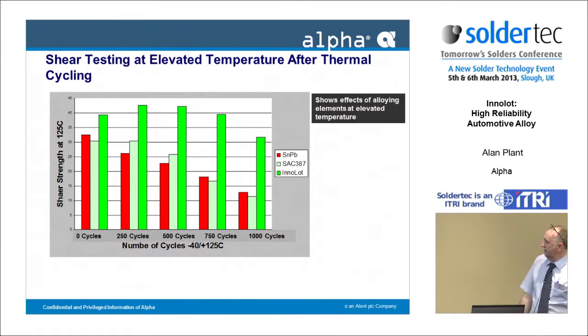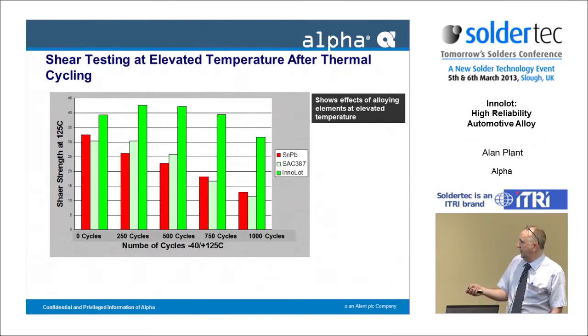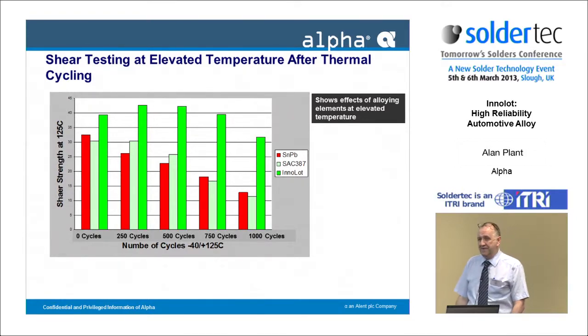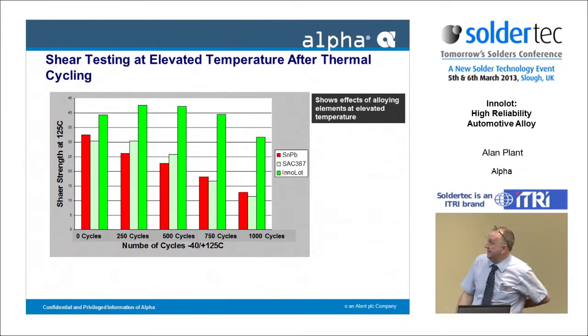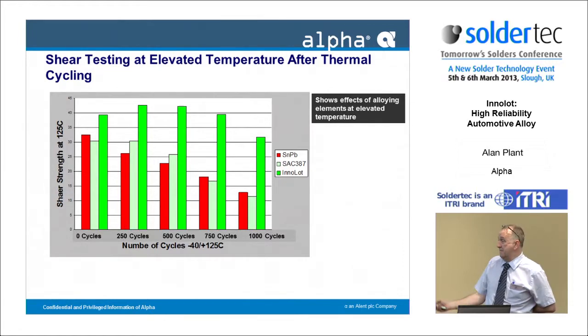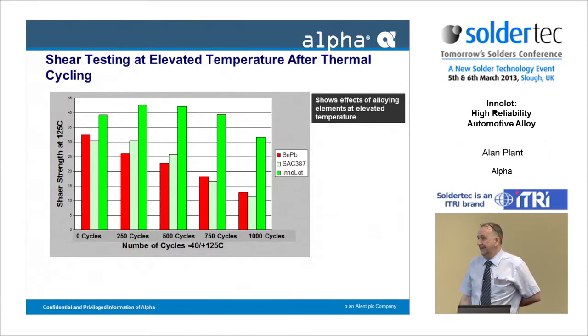And testing again after thermal cycling, but at elevated temperatures, you can see that the Innolot clearly outperforms the others. Now, one interesting thing here I don't know the answer to is that the Innolot appears, and it's only a small sample here, to actually get stronger, then drop down. Whether or not this is some of the aging phenomenon that we've heard about, almost certainly it will be, because if you look at other solid solution strengthened and also precipitation hardened materials, there's a lot of age hardening goes on there, so it may well be that there is some growth of the